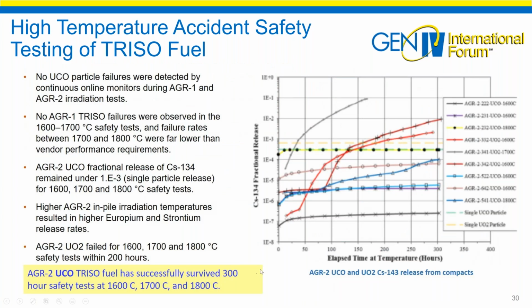We're going to notice in this graph that we have AGR-2 results and single particle failures for UO2 and UCO. Now this looks like a big mess here, but what I want to point out here is these three lines here are the UO2 fuel, and they definitely had more than one particle released. It wasn't as robust. There were no UCO particles that were seen in AGR-2 and AGR-1. No AGR-1 particles were seen to be failed in our safety test between 1600 and 1700 C.